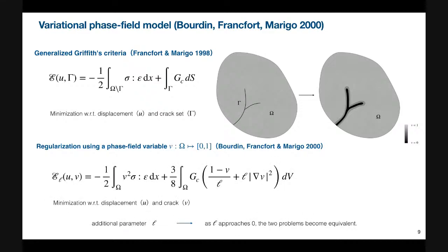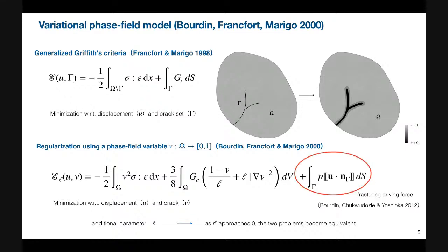And by introducing this phase field variable, the energy functional can be regularized using the regularization length parameter L. If we send this L to zero, then these two problems become equivalent. And if we extend this to hydraulic fracturing, we need to add an extra term that accounts for the work done by the fluid pressure within the fracture. So this becomes our total energy in the hydraulic fracturing problem.